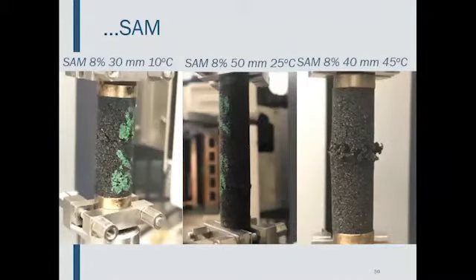These are some examples of the failure because of the test. We get this in the samples. Sometimes we see the failure here with cracks in the middle. Most of the time it's in the middle of the samples, but sometimes you can see it close to the bottom or even close to the top of the sample.